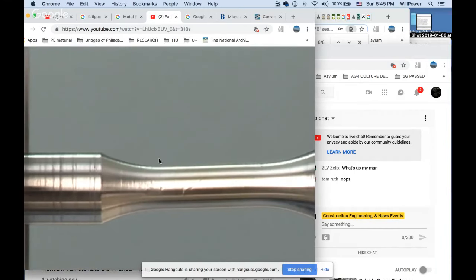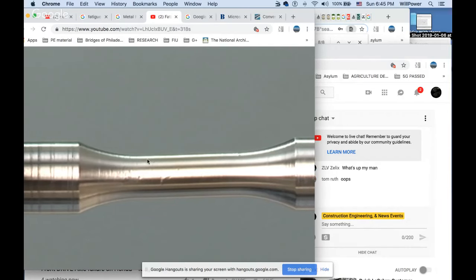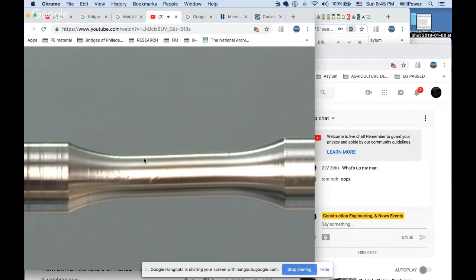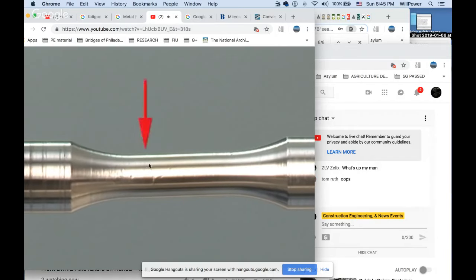Now I'm going to zoom in because I want you to watch the beginning of a stress fracture. And this is what you look at on airplanes, everything, to keep track of this stuff. But here we go. Still seems to be intact. Right there. There's the beginning of it, right here. In reality, however, several cracks have already developed starting from the surface, the so-called fatigue cracks. See it? With each load cycle, they grow a bit further into the specimen. The biggest crack gains the upper hand, grows the fastest, and so there's your fatigue crack.